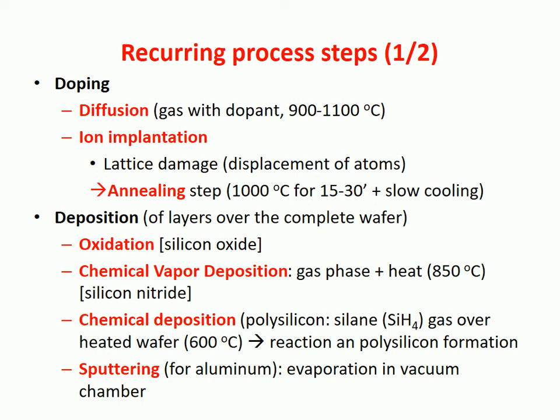to facilitate diffusion, and typically we have a concentration profile in terms of the depth of the silicon wafer that is something like this. Okay, this is the thickness of the wafer. Let's assume that this face is exposed to the doping gas, then the dopants penetrate, and of course the concentration is higher close to the surface and decreases when it goes inside the wafer. And typically, the more time you keep the process running, the deeper the dopants penetrate. But still, we have this gradient.